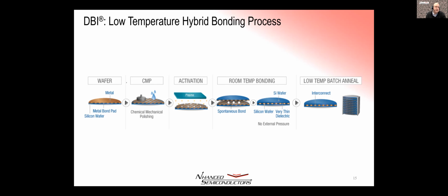We do a plasma activation. What that does is it takes the silicon dioxide, or it could be silicon nitride, and it opens up the bonds. And we end up with silicon with, instead of oxygen hanging on it, hydrogen hanging on it, or nitrogen hanging on the tips. When you bring two wafers together at room temperature, it will spontaneously bond. There's a van der Waals bond that's formed immediately.